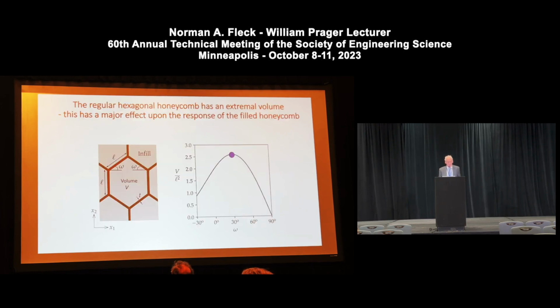Now if we add an infill, what happens? Well, the first way to think of this problem is to say, let's plot the volume of the hexagonal honeycomb as a function of that angle omega. 30 degrees, which I've marked, is the regular hexagonal honeycomb case, and it's an extremal structure. It occupies the largest volume V for a given cell size length, which is not changing. So if I just imagine a pin-jointed truss, each cell is length L, and I vary that angle omega, I see that as I increase omega, I go through a maximum inflated volume, and if I continue to increase omega through 30 degrees, the volume drops.